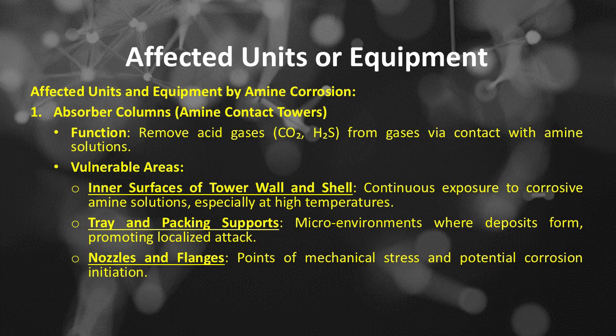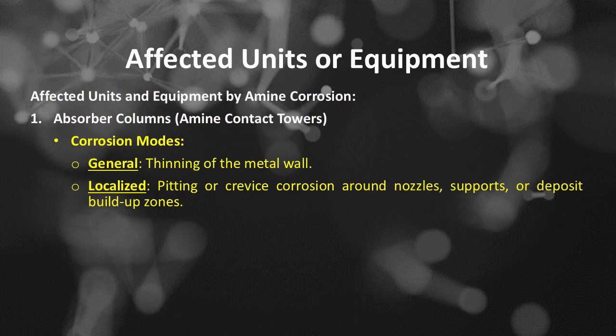The function of absorber columns is to remove acid gases, CO2, H2S, from gases via contact with amine solutions. Vulnerable areas of absorber columns include inner surfaces of tower wall and shell, continuous exposure to corrosive amine solutions, especially at high temperatures, tray and packing supports, microenvironments where deposits form, promoting localized attack. Nozzles and flanges, points of mechanical stress and potential corrosion initiation. Corrosion modes commonly occurring on absorber columns include general thinning of the metal wall, localized pitting or crevice corrosion around nozzles, supports, or deposit buildup zones.